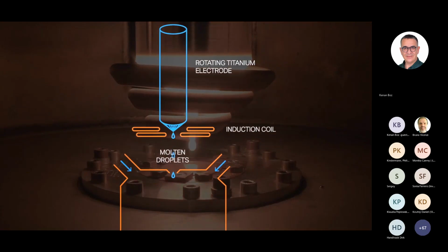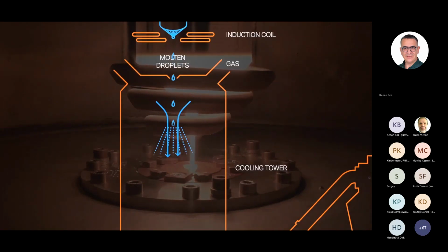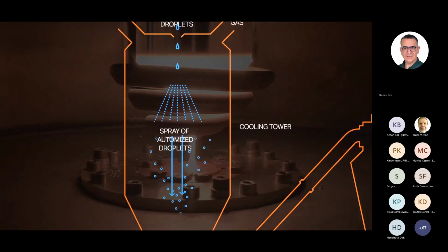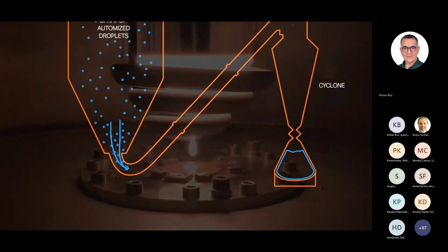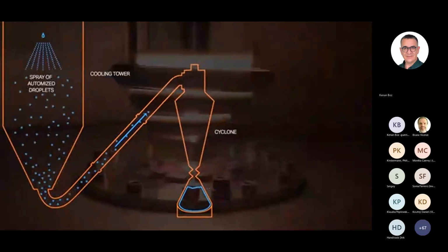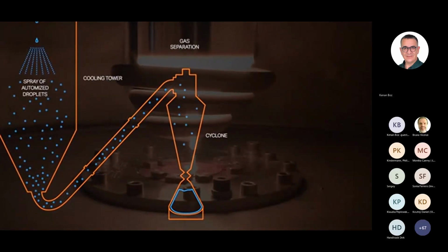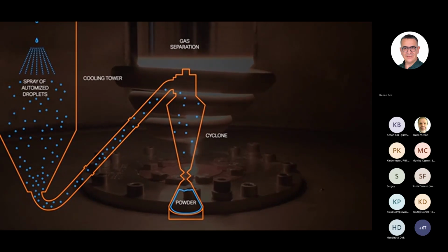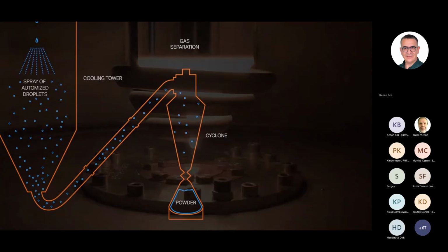In this case, it's titanium, so it has to be a crucible-free process. The atomization gas then impacts on that flow of molten metal material. As it falls through the cooling tower, it solidifies, and again, the powder is separated from the gas, and the powder is collected. And in this case, often the titanium powders produced by electrode inert gas atomization are handled under completely inert conditions. So the blending and sizing and packing are all done under argon gas.